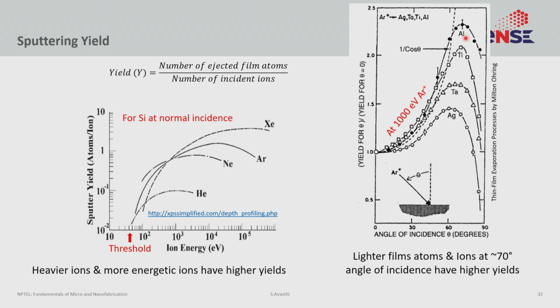There is also dependence on theta. So not all the flux of argon plus ions that is coming, not all of them are created equal. Those that are actually at higher angles can sometimes cause more sputtering to happen. Without going into unnecessary detail, one of the reasons you can think this might be is because ejection requires sort of a glancing deflection, and certain angles are a little more probable than others. So it turns out that zero, which is the normal incidence, is not the one that gives you the highest yield. The highest yield is somewhere around 60 degrees, and modern sputtering systems take care of this by an elaborate system of magnets that actually tunes the direction at which argon plus ions come. Those magnets are also needed for something else called magnetron sputtering, but we'll come to that later.